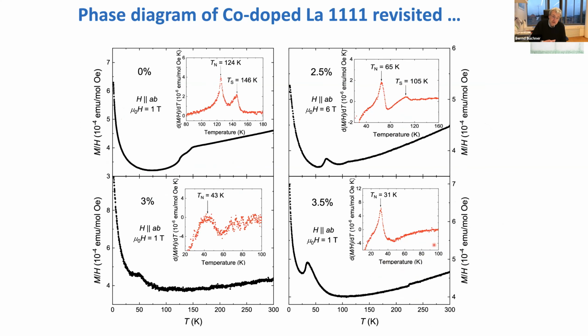You can also, of course, measure the magnetization just to follow the phase diagrams. So for the parent compounds, you clearly see these two phase transitions. And if you start to dope, the structural transition becomes very broad again.